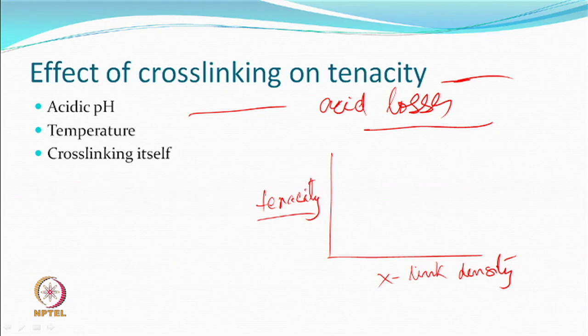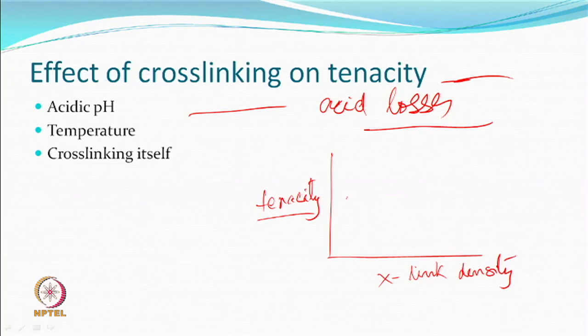So, this is just by cross-linking, even if there is no acid loss, if there is no loss due to temperature or high temperature, just by cross-linking you can get something like this, particularly in cotton you observe this. This is a hypothesis proposed by Rebenfeld, and what it says is that if you have less cross-link density, and you keep on increasing cross-links, the tenacity of, let us say, the yarn or the fabric will increase. After a certain point, it will start decreasing. And as they say, the cotton actually lies here.